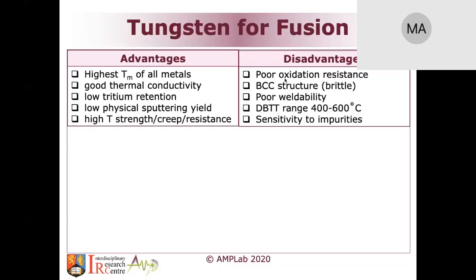Furthermore, it has a fairly high ductile-to-brittle transition temperature, which means that if you are below 400, which is quite a high temperature, the material behaves in a brittle fashion. So that's really a problem, because in additive manufacturing, things will have to cool down. And as they cool down to temperatures below 400 or so, and there are lots of residual stresses, there is a big chance that cracks can open and defects can form. Finally, it's very sensitive to impurities. Oxygen, carbon, and other elements actually deteriorate the properties quite rapidly.